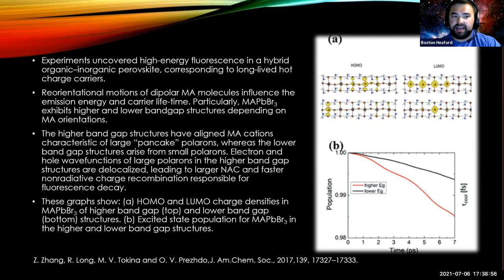The higher band gap structures have aligned methylammonium cations, whereas the lower band gap structures arise from small polarons, whereas the high band gap structures arise from large polarons. And then the electron and hole wave functions of large polarons in the higher band gap structures are delocalized, which leads to a larger non-adiabatic coupling and faster charge recombination, which is responsible for the fluorescent decay. And these are some graphs of the population as a function of time of the two systems.